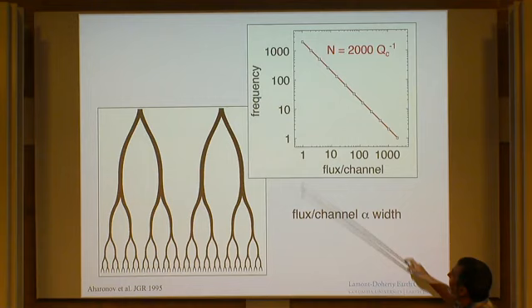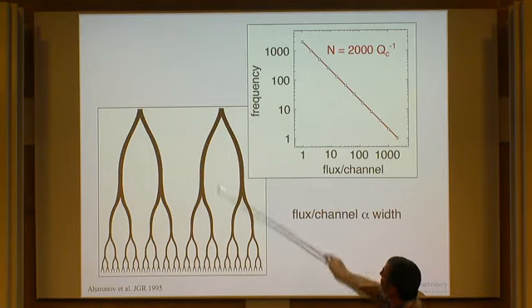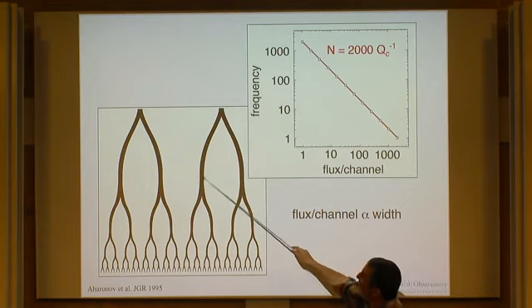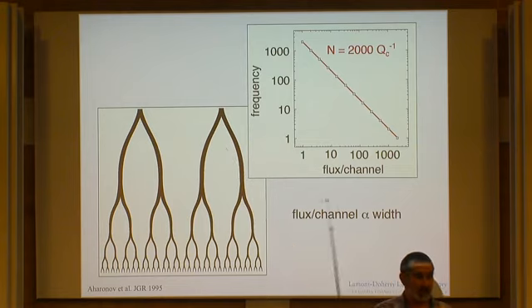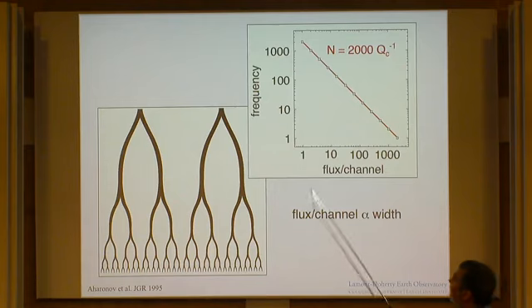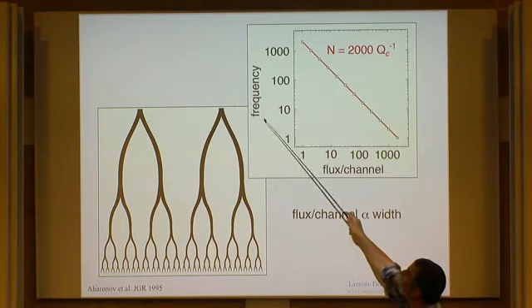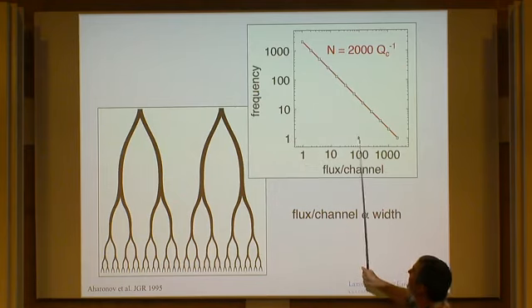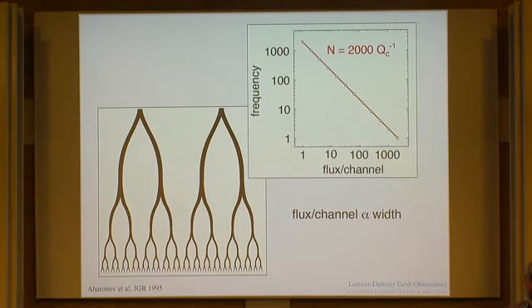And of course, if I say that the width of these channels is somehow proportional to the flux in the channels, then I get a nice power law, a stupid power law, but a power law distribution between the frequency and the flux, or the frequency and the width. So that's something we might be able to go out in the field and look for.